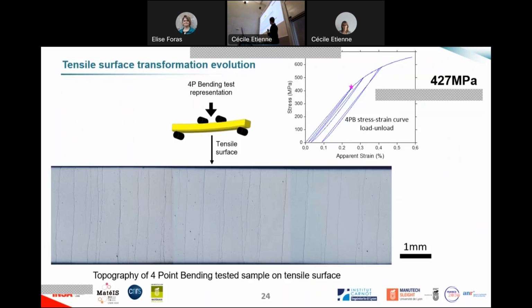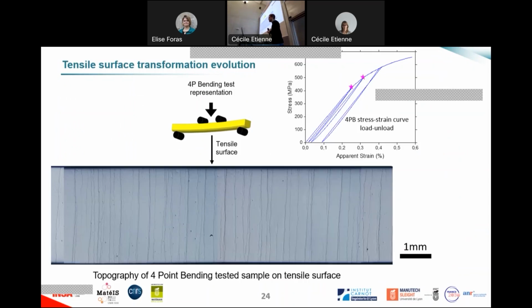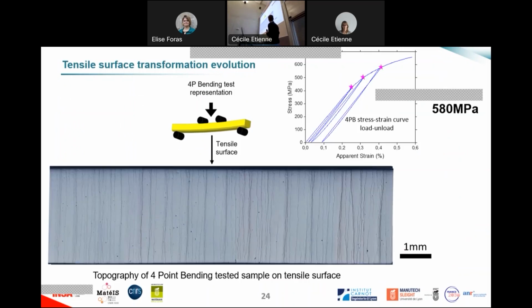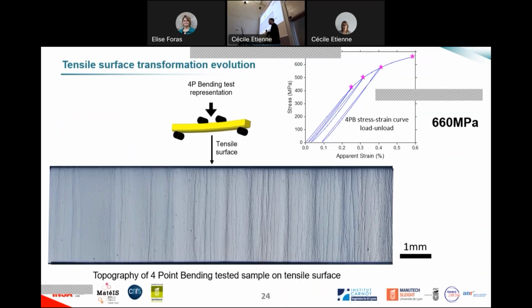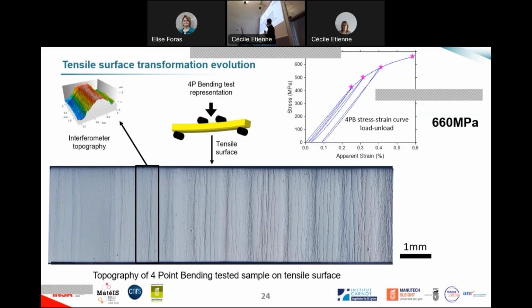So here what you see is the surface of a ceramic that is subjected to 4-point bending tests. And what you see, it's not cracks, it's transformation bands where we have transformation. So here on the mechanical characterization curve, you see that we are at the first point, that when we increase the load, we have more transformation, and more transformation. And so we made studies to understand why the transformation was located on some peaks and not other peaks. So what you can see here is that it's volumic transformation, it's not only lines. You see that there is really a volume pattern on the transformed layer. But this wasn't expected because it didn't transform this way before.